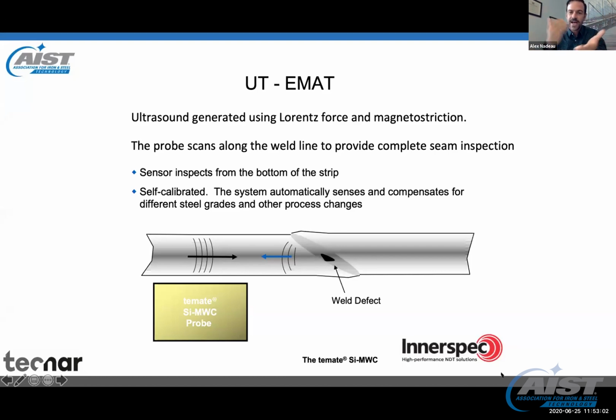So it could be a lack of fusion, it could be cracks, it could be porosity. Anything that's there will trouble the ultrasound and send some back to the detector. So it's a pretty simple concept. The detector is about 4" in width, so it cannot be exactly inspected while we're welding.